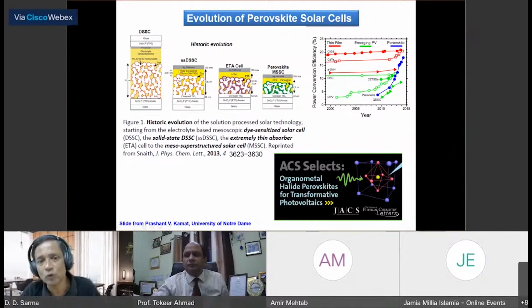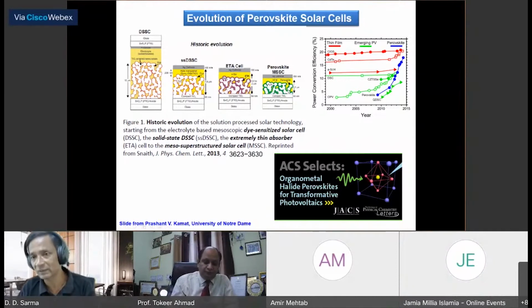Then we went to solid state dye-sensitized solar cells that were about half a micron or 1 micron thick. Extremely thin solar cells, based on similar technology with improvement, came to about half a micron. Whereas this new material, its absorption power is so strong that it can make the solar cell less than half a micron thick.